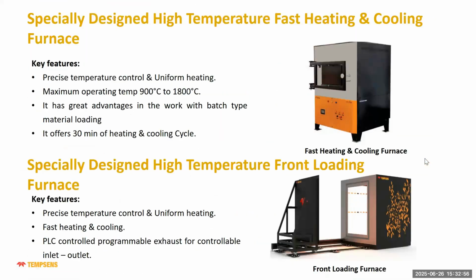These are specially designed high temperature fast heating and cooling furnaces. If there is a requirement of very fast heating, and cooling also required very fast, we can give a special system in which the heating element can be silicon carbide, which can heat the material inside 30 minutes, and then also cool the material from 1200 to 600 degrees centigrade in 30 minutes by using forced air circulation. We purge the outside air inside the furnace, and there will be an exhaust fan on the outside. It will extract the heat from inside the furnace, and it will cool fast. So it offers a 30 minute heating and cooling cycle. We can also give a front loading furnace with very big sizes, around 1 meter by 1 meter by 1 meter for 1800 degrees centigrade.